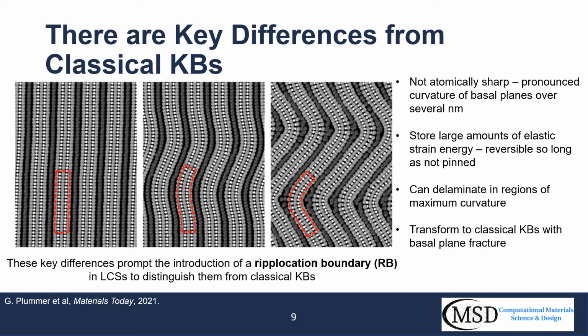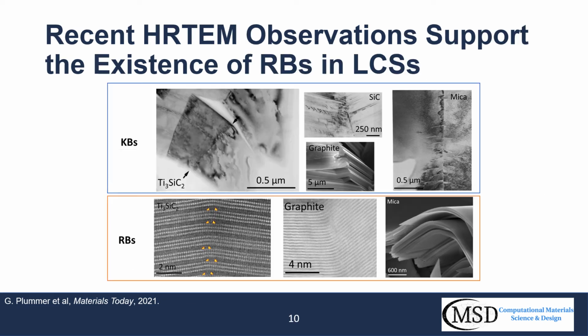These key differences have prompted us to start referring to these boundaries as ripplocation boundaries to distinguish them from the classical kink boundaries. And this is inspired by the idea of ripplocations, or atomic scale ripples, which have been observed in the basal planes of van der Waals solids such as graphite.